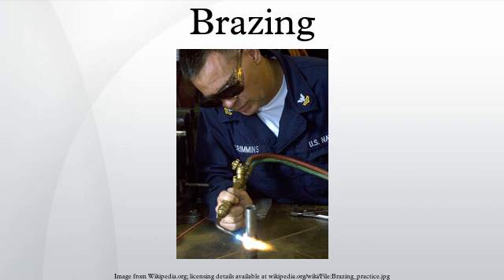Cleanliness of the brazing surfaces is also important, as any contamination can cause poor wetting. The two main methods for cleaning parts, prior to brazing, are chemical cleaning and abrasive or mechanical cleaning. In the case of mechanical cleaning, it is important to maintain the proper surface roughness as wetting on a rough surface occurs much more readily than on a smooth surface of the same geometry.